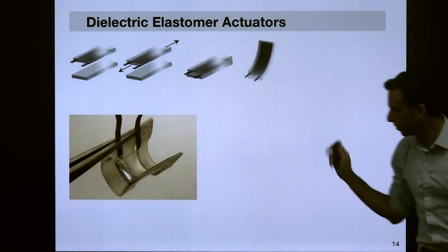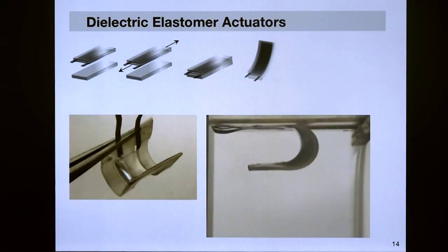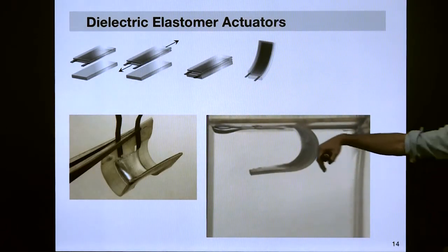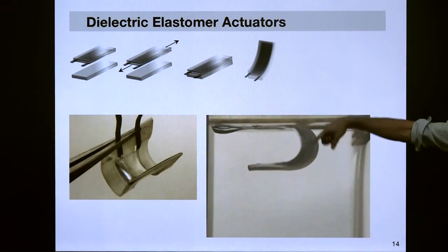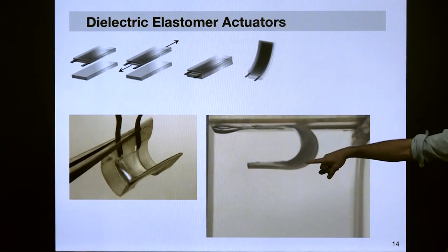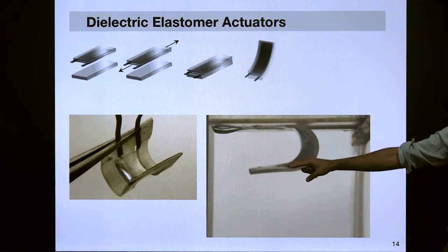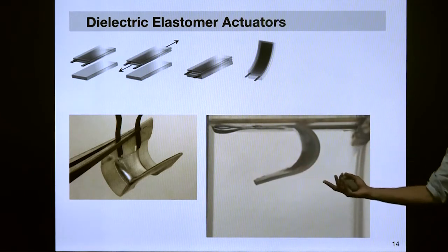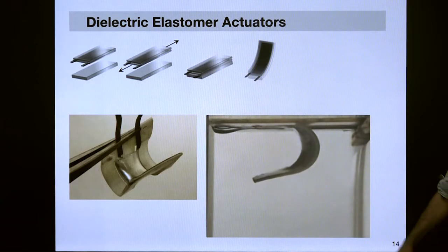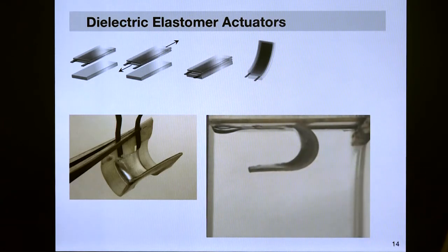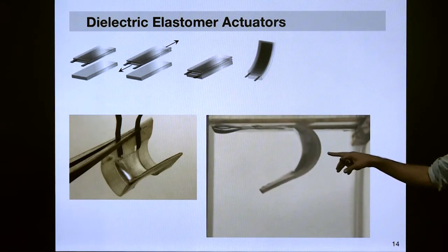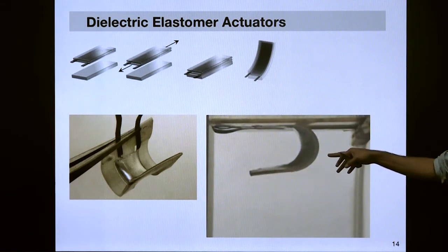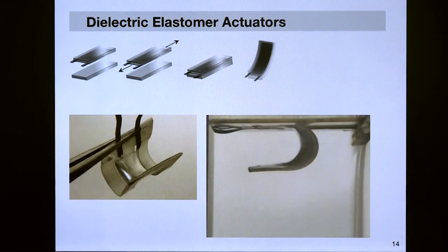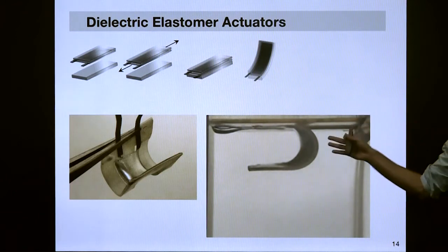Just to demonstrate that, again, this is a demo for the soft robotics class, but this is the dielectric elastomer actuator, which has some natural bending curvature due to the pre-stretch of the dielectric film. I apply 2 kilovolts, you get very modest deflection. I apply 3 kilovolts, a little bit more, so that's promising. But now when I go to 4 kilovolts, you'll see what happens. Now I'm getting very large deflections. But then, you saw that spark there, I got that dielectric breakdown, and basically I fried this actuator at this point.